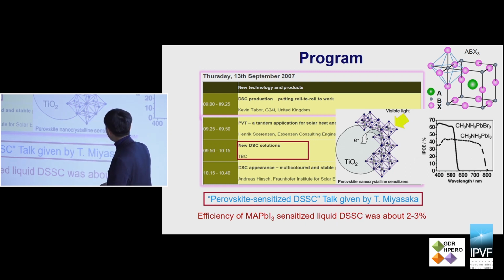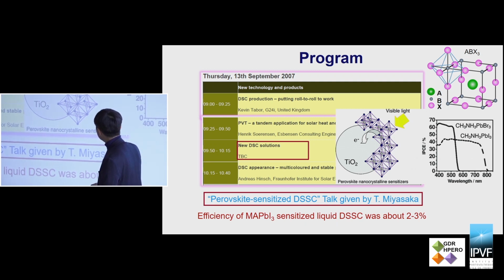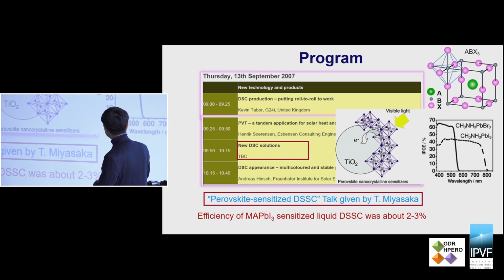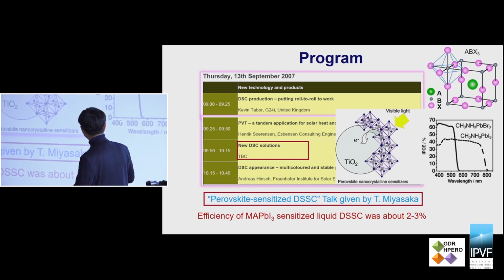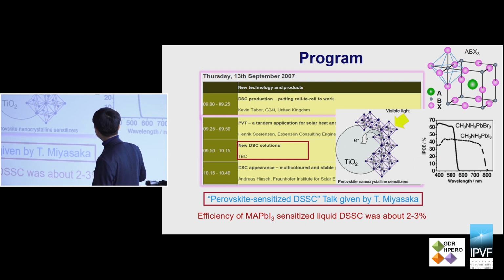And then he used this material as a sensitizer, sitting on the titanium oxide, and he showed us the IPCE spectrum, the external quantum efficiency as a function of wavelength here. And then the methyl ammonium lead iodide, we have the organic cation, especially in this specific perovskite material. As you can see here, the absolute IPCE is even lower than 50%.